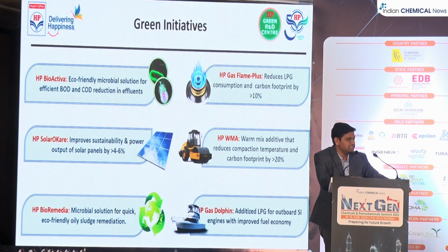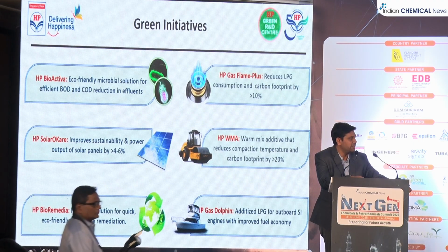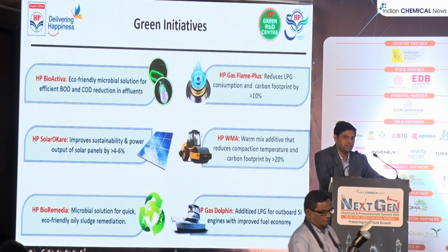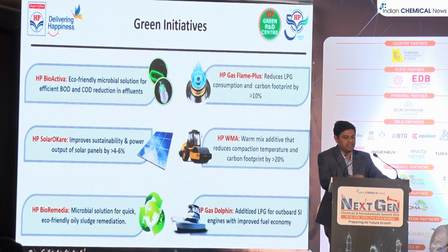HP Flame Plus and HP Dolphin are basically our LPG additives, developed based on the theory of flame propagation and combustion efficiency improvement. WMA is our warm mix additive, which is mixed into bitumen before laying the road. It requires a temperature of 170 degrees Celsius. If you use HP WMA, we can reduce the temperature to 150 degrees. So there is a 20-degree reduction in temperature, which helps in saving energy.